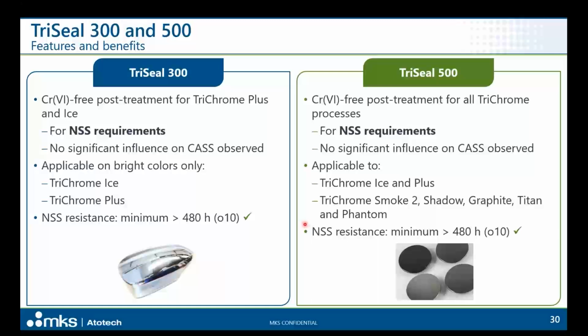In this case, we are talking about a post-treatment which will, of course, improve the performance in the neutral spray test, and is applicable on bright colors only. So that means that the Tri-Seal 300 will work for the Ice and the Plus. And with this, we can achieve more than 480 hours in neutral spray. And also, we can propose to you a Tri-Seal 500, which is also a chrome 6-free post-treatment, but in this case, for all the trichrome processes.